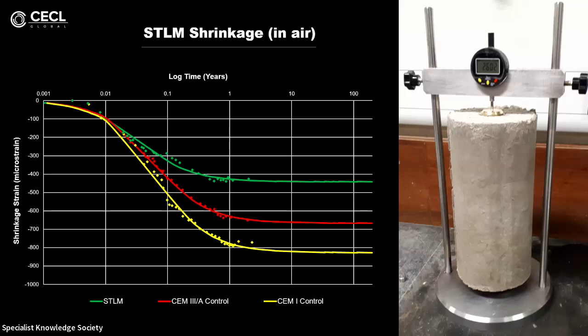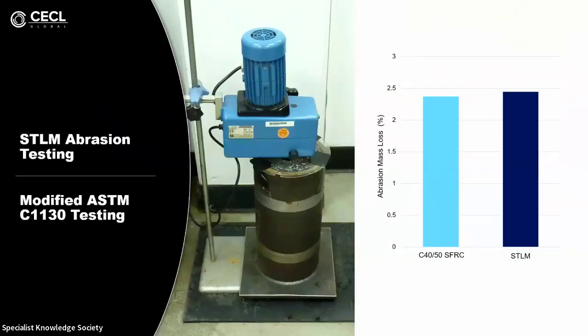And with these long-term shrinkage strains that we're seeing, if we consider that in a restrained tunnel situation, we'd expect the lining to be uncracked in the long term from shrinkage strains, which is a big positive in terms of the water tightness and durability of a slipform tunnel lining.